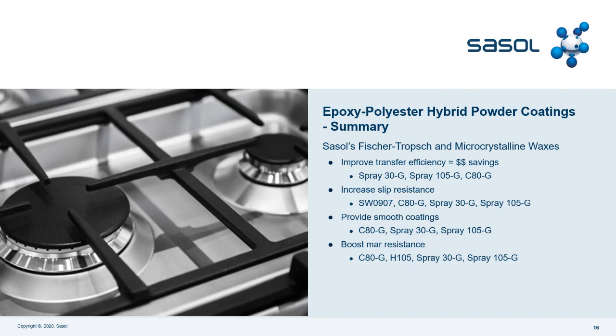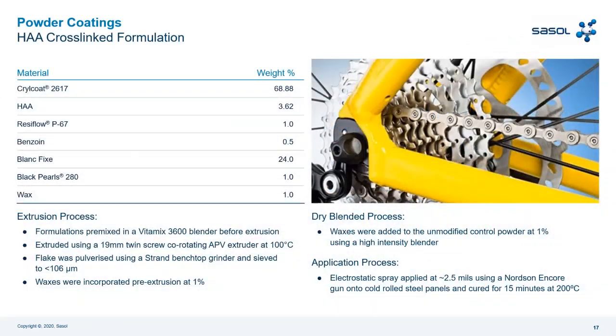Then to provide a smooth coating, we have Sasol Wax C80G, the best result from Sasol's perspective, and the others follow. Then for boosting mar resistance, we have Sasol Wax C80G as the best result in post-extrusion, so post-added, and then follow H105, coarse powder, Spray 30G, and Spray 105G. So you can see the summary. I will detail the summary also at the end of this study. This is a summary for epoxy polyester hybrid powder coating resin. Then go to the other test, the other formulation.